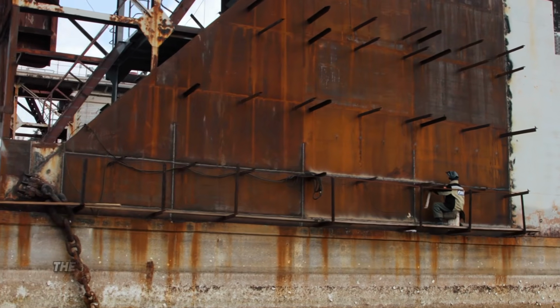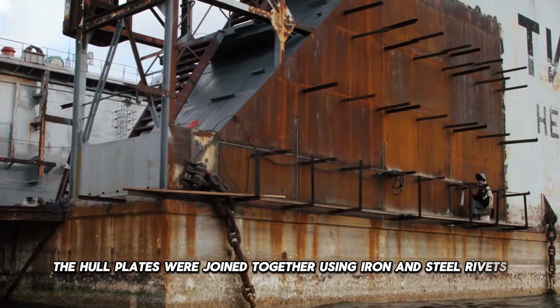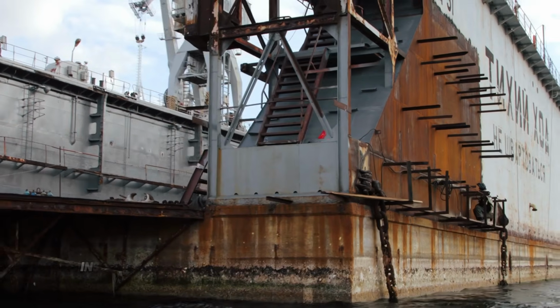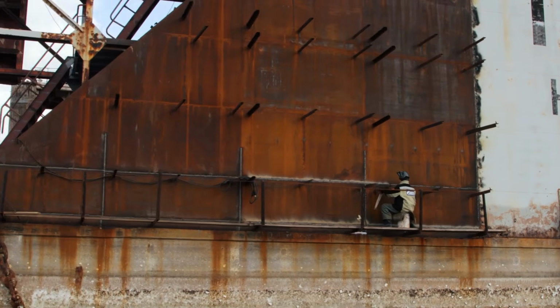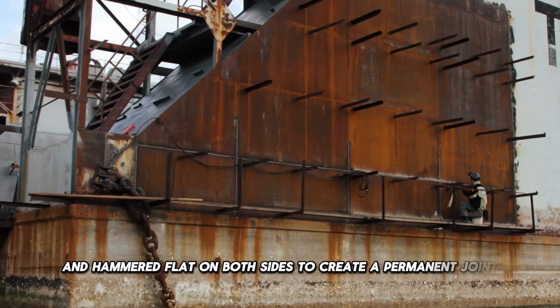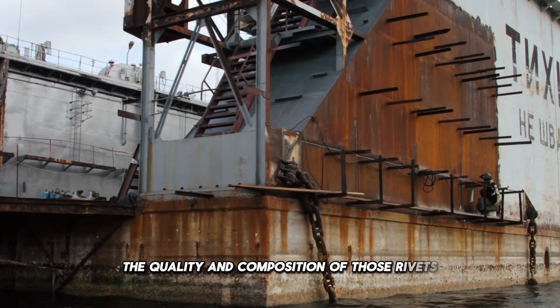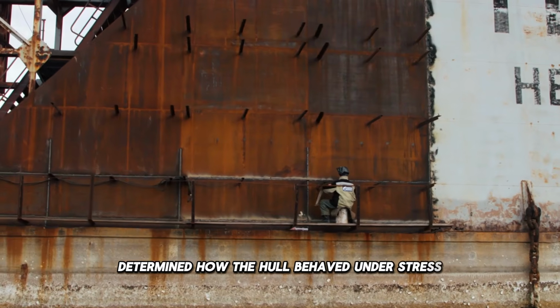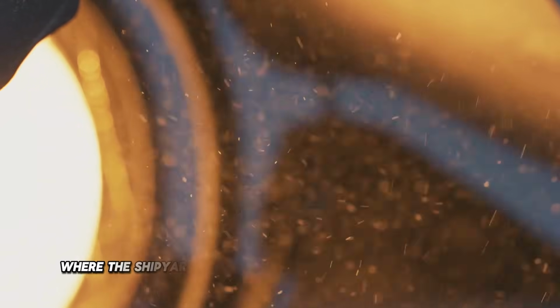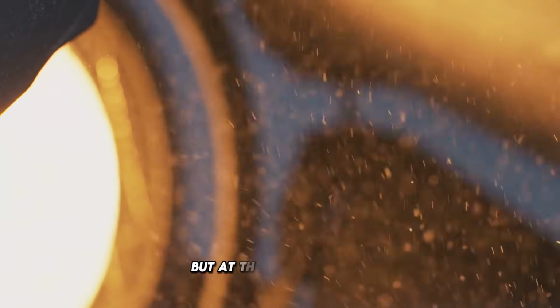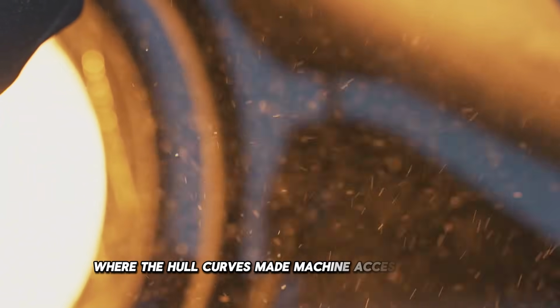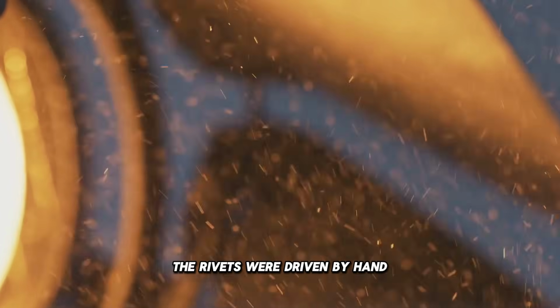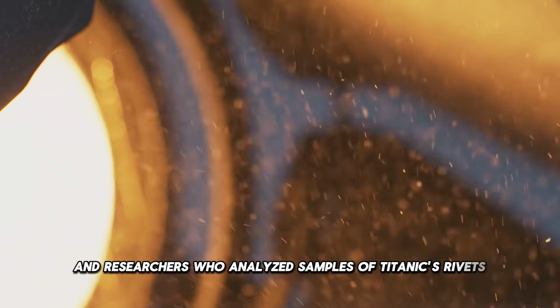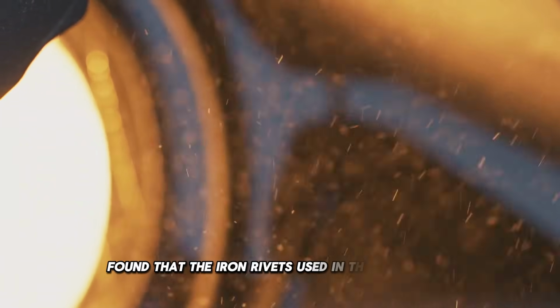When Titanic was built, the hull plates were joined together using iron and steel rivets. Metal pins heated until red hot, inserted through pre-drilled holes in overlapping plates, and hammered flat on both sides to create a permanent joint. The quality and composition of those rivets determined how the hull behaved under stress. In the midsection of the ship, where the shipyard's hydraulic riveting machines could reach, steel rivets of good quality were used. But at the bow and stern, where the hull curves made machine access difficult, the rivets were driven by hand. And researchers who analyzed samples of Titanic's rivets recovered from the wreck found that the iron rivets used in those sections had a significantly elevated slag content.